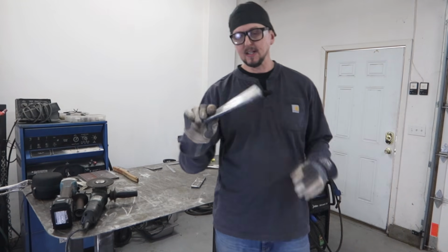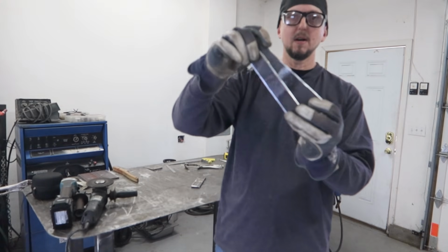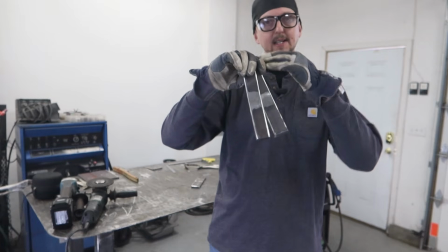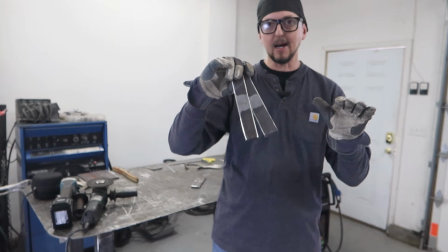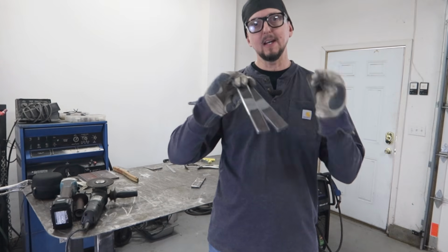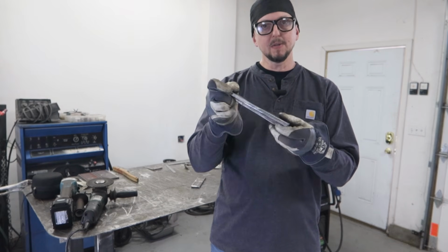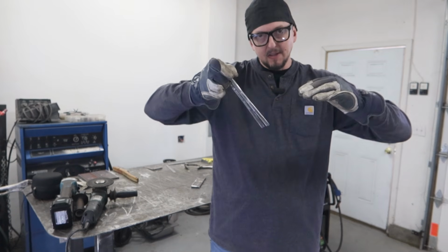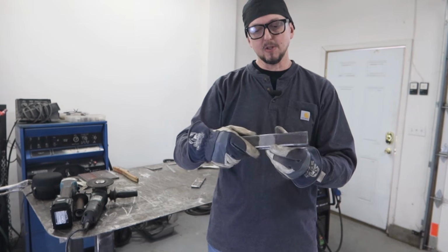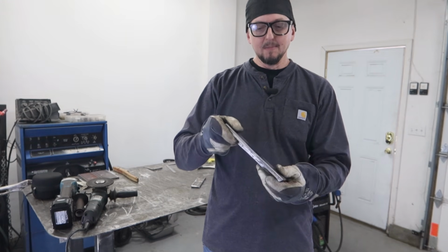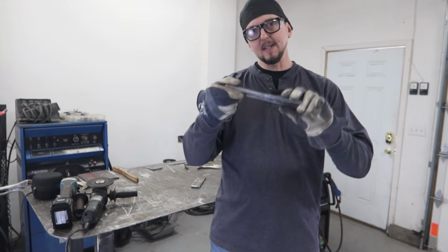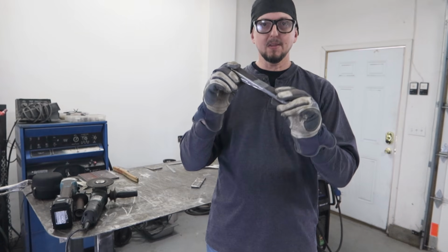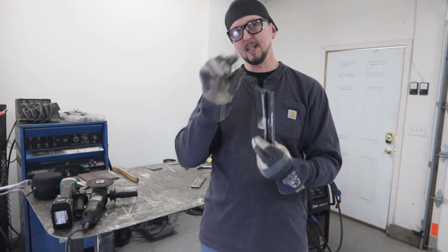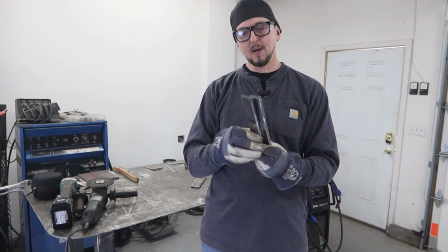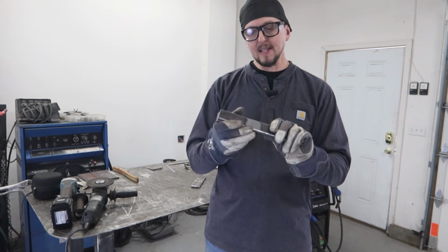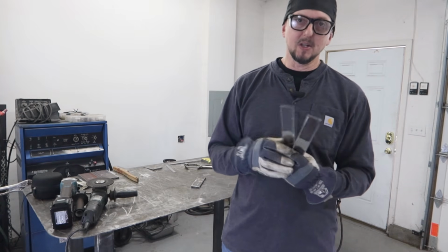The other thing that I wanted to mention is if there's any low spots that show on the face or on the root, wherever you're grinding, just go to flush with the base surface and then stop. If you continue to try to chase these low spots, which they always have next to the weld, from that base metal kind of turning up and the distortion of the weld, you're always going to have those low spots, so don't chase those and end up with a 1/4 inch plate instead of a 3/8 plate, because if you're doing a certification and they see that the center of your test coupon is way thinner than it should be, then that can be grounds for a fail just in that.